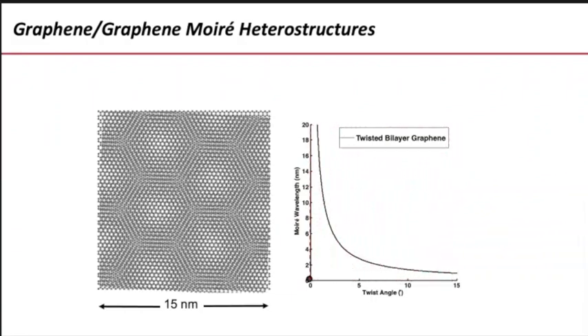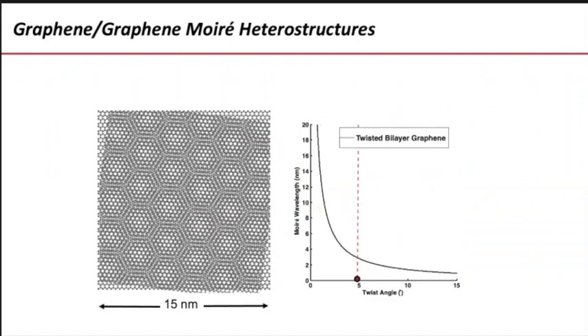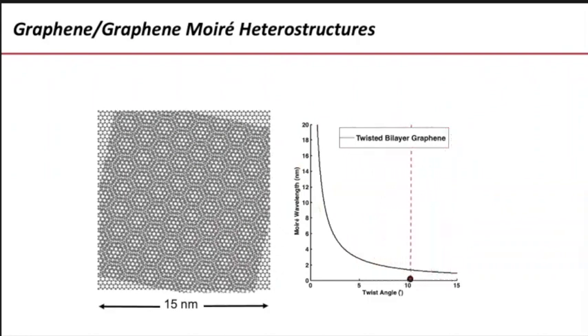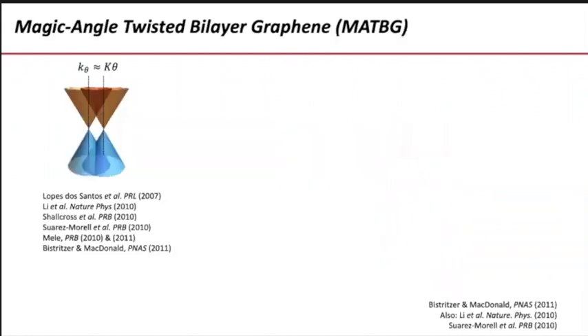Graphene, as you know, has in its electronic structure this Dirac cone. So let's see what happens to this electronic structure when you twist. If we start from a small twist angle, it turns out that the Dirac cones in reciprocal space are very close to each other, roughly separated in momentum space by an amount proportional to the twist angle. And this is the situation that would occur if electrons in one graphene sheet did not know that the other graphene sheet was there. And these energy momentum dispersions would just interpenetrate each other.